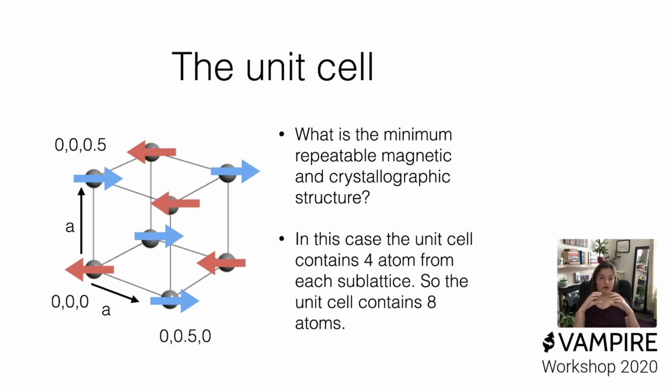So if we imagine we've got our unit cell, and then we copy it upwards, so we repeat it upwards again, then we would have an atom at 0, 0, 0, an atom at 0, 0, 0.5, and then another red atom, which is a copy of the 0, 0, 0 atom, at 0, 0, 1. So this is why we've put our blue atom at 0, 0, 0.5 and not at 0, 0, 1, as you would expect, because otherwise when you copy it upwards, the red and the blue atoms would be in exactly the same spot. And this happens in Y and in X as well.